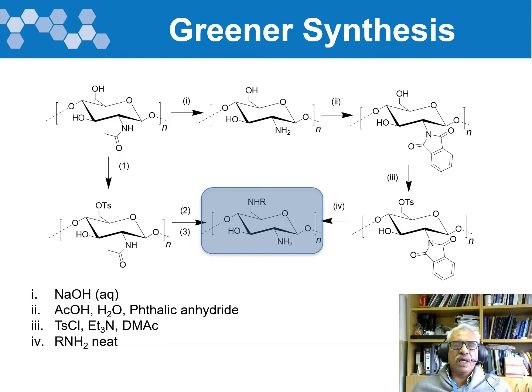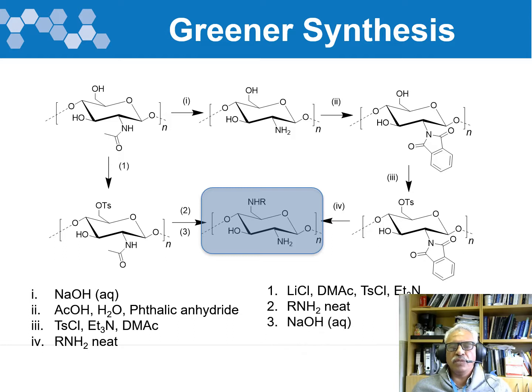So we can also do a tosylation directly on chitin and then do the treatment with an amino or alkylamine to give you the target product. The better solvent here would then be dimethylacetamide with tosyl chloride, triethylamine, and lithium chloride to do the tosylation step here. And of course, the substitution with the alkylamine gives you the product. And of course, we still don't use ionic liquids to do the deacetylation.